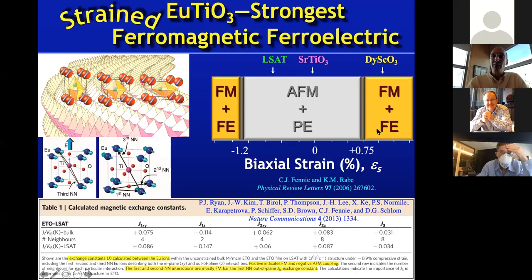So this is a great example of how ferroelectricity can be enhanced at the same time as ferromagnetism in this quantum material europium titanate. So you can see how biaxial strain, not only is it like strontium titanate going to break the center of inversion here by taking the titanium off center, but also it's going to change the balance between the exchange constants being ferromagnetic or antiferromagnetic. And so that's why, at least on the computer, when you strain it enough, it should go off center enough that it becomes ferromagnetic and ferroelectric at the same time.